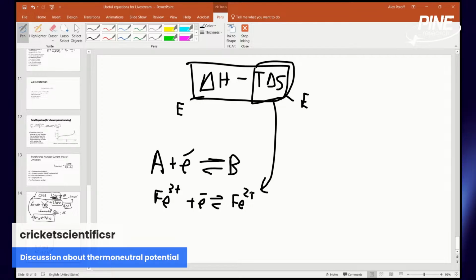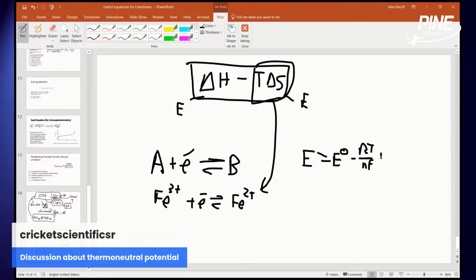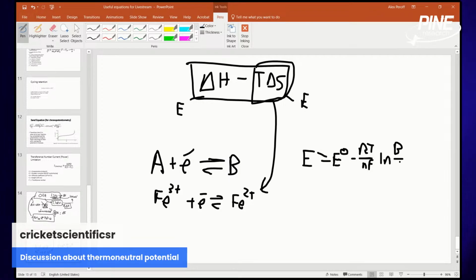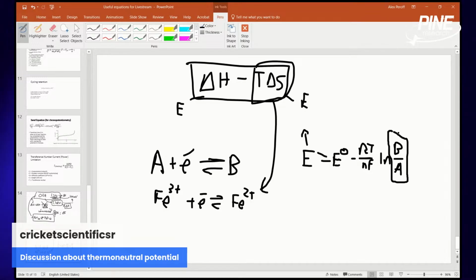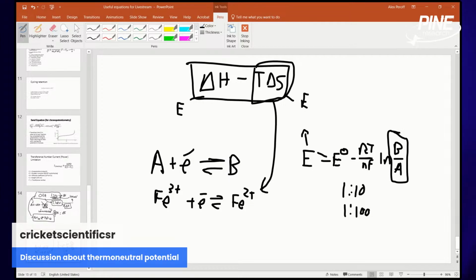I think the last thing that I mentioned in my LinkedIn message to you was that we can think about the Nernst equation, which says that the potential is equal to E naught minus RT over nF times the natural log of the activities of B over A, or iron 2 plus over iron 3 plus. And when we apply a potential, when we change this potential, we're shifting this ratio. And when we shift this ratio, when we go from 50-50 to something like 1 to 10 or 1 to 100 in A to B or B to A, there's a necessary entropic cost to that. In a way, you have more entropy when you have a 50-50 mix, a 1-to-1 ratio of A and B, or iron 2 plus and iron 3 plus.